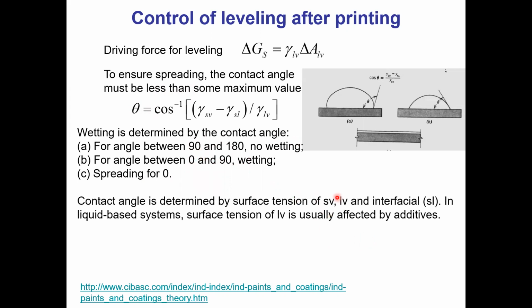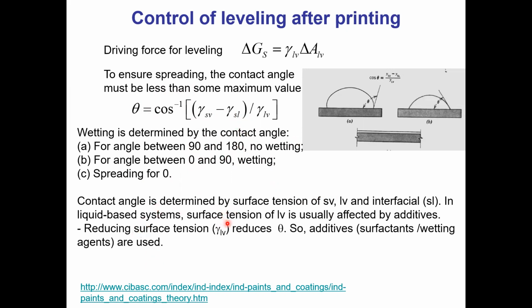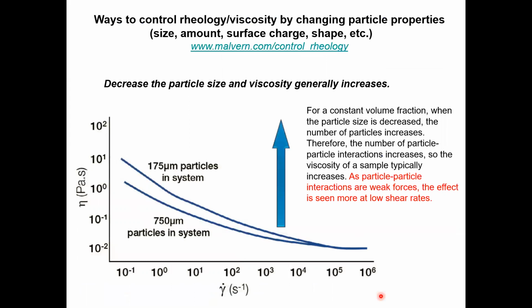You can see the contact angle depends on all kinds of surface and interfacial energies. And you can actually control those energies to some degree. So you can add additives like surfactants and wetting agents to control these interfacial energies. Adding surfactants will reduce the gamma between solid and liquid, helping further decrease theta. But you have to be careful that you add an optimum amount so that you don't decrease this gamma so low that theta becomes very close to 0. That will lead to bleed out. So there is some compromise of how much you should add to control the theta.